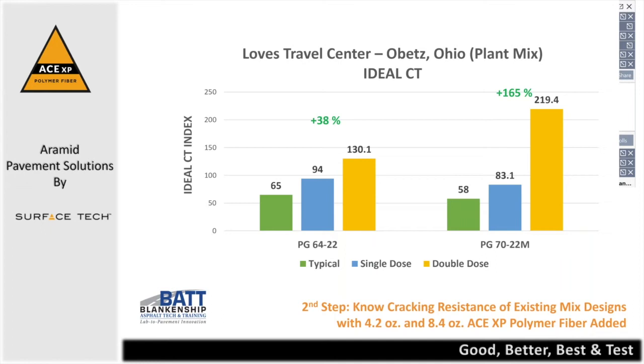And so it's a 6422 versus a 7022 modified, or if you will, polymer modified. As you can see, I loaded the typical values that we see for those two binders in green, and then the measured values are blue and orange. And you can see a 38% increase to typical values, and then all the way up to a 165% increase as we get up to the 7022 double dose.